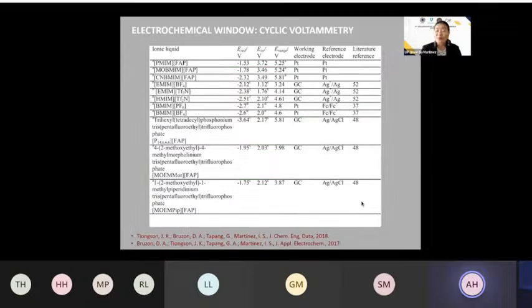And of course, in terms of electrochemical window, as you can see here, we have very wide electrochemical windows. In fact, the cyano-functionalized ones can really compare with this particular FAP ionic liquid that's also out there and not synthesized by our group. And we think that the reason for this very wide window is the anodic passivation due to the cyano group and, of course, stronger ionic interaction, once again, because of this functional group.